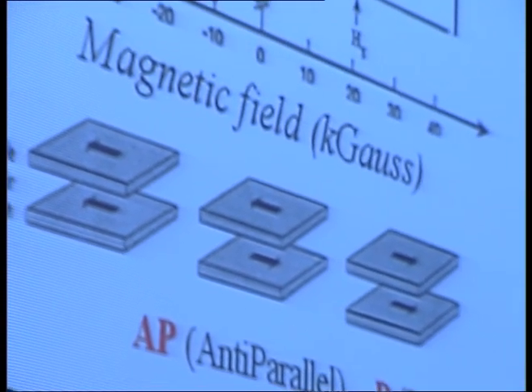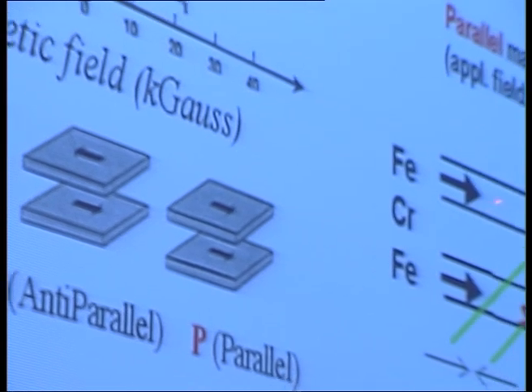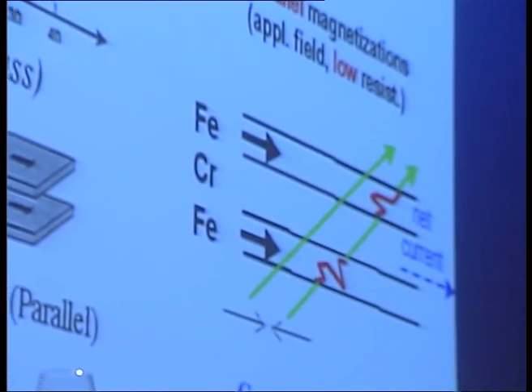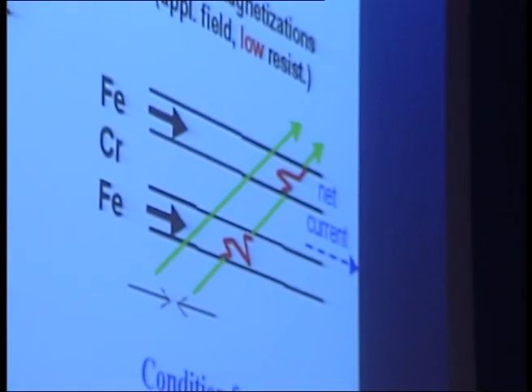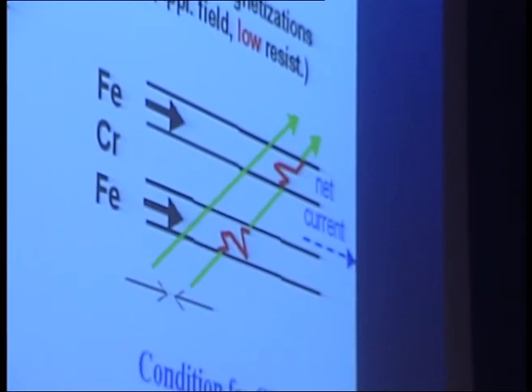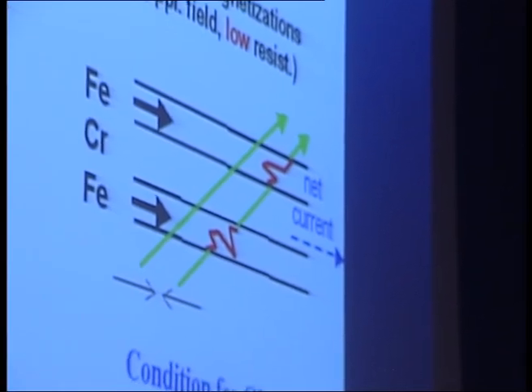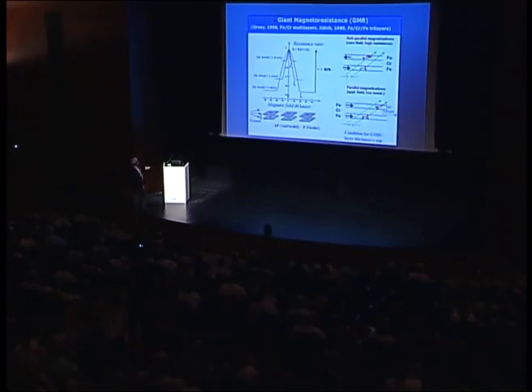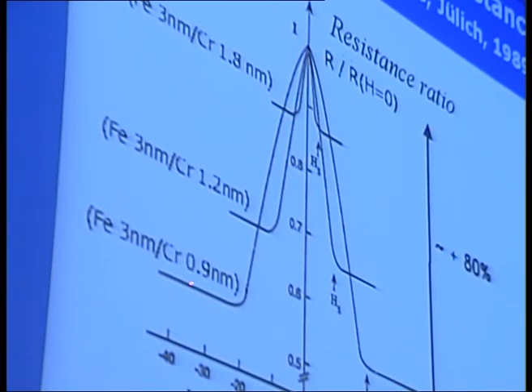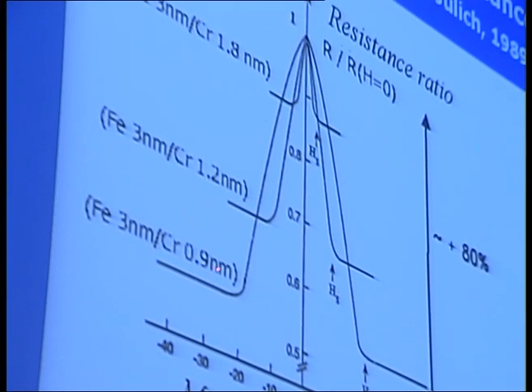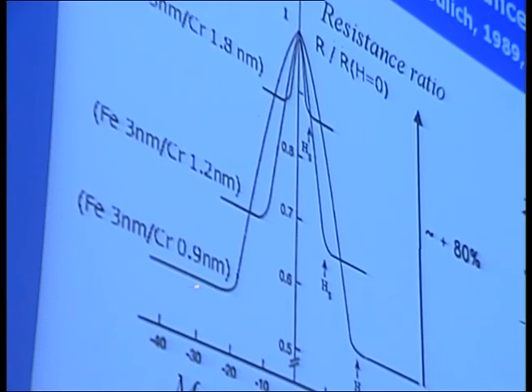And of course, the condition is that the thickness of the layer should be smaller than the mean free path, of the order of a nanometer. You can see that indeed the largest value of the GMR is obtained for very small thicknesses, for example, less than 1 nanometer for this curve.